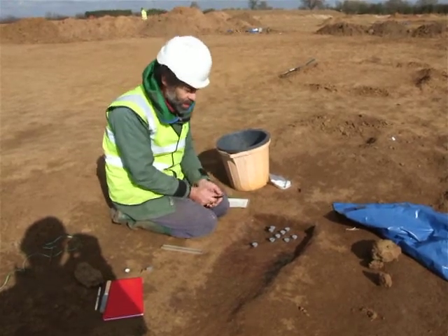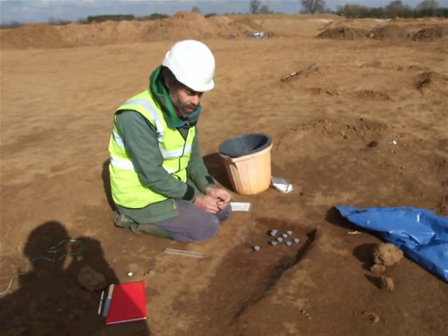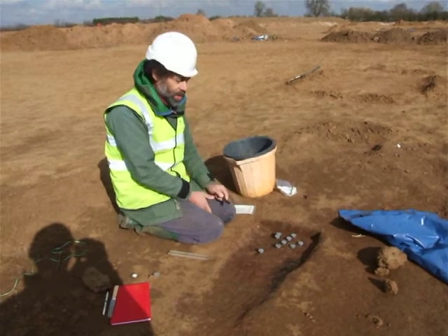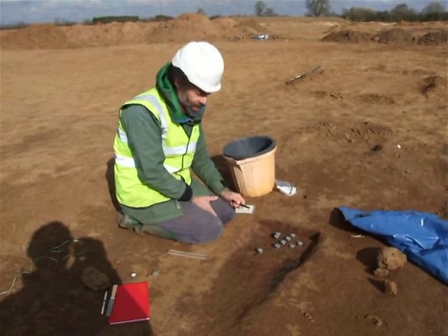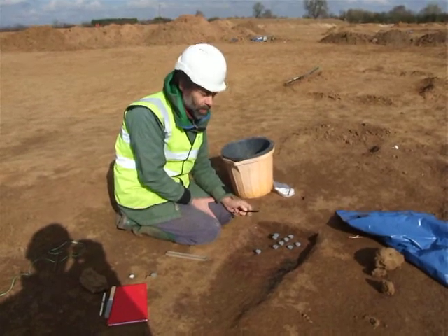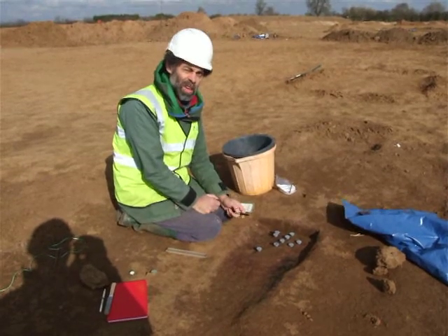It's possible if I take a dozen samples that one or two may need to be rejected. Maybe they've moved and I can't actually see the movement. It could be that some samples aren't magnetized at all because they were too cool — they haven't been heated. Another possibility is root disturbance which also randomizes magnetization. In order for the magnetization to be reset to the Iron Age direction, the clay has got to be heated and then cooled to a temperature of about 600 degrees centigrade. That's the critical temperature above which the material becomes non-magnetic, and then when it cools down through this critical temperature, about 600, it acquires magnetization in the Iron Age direction.